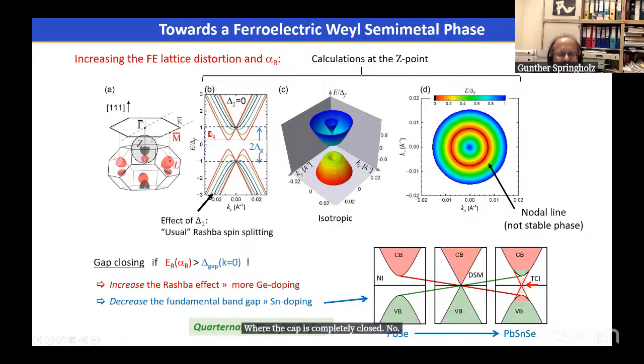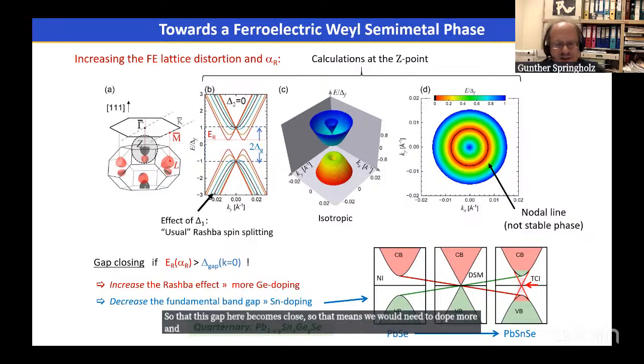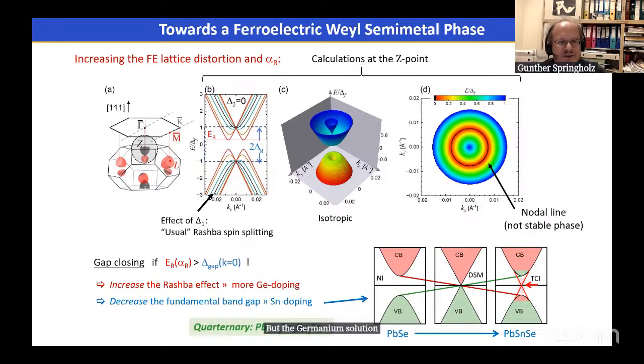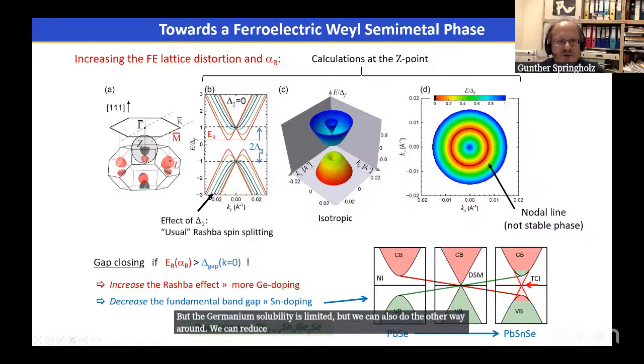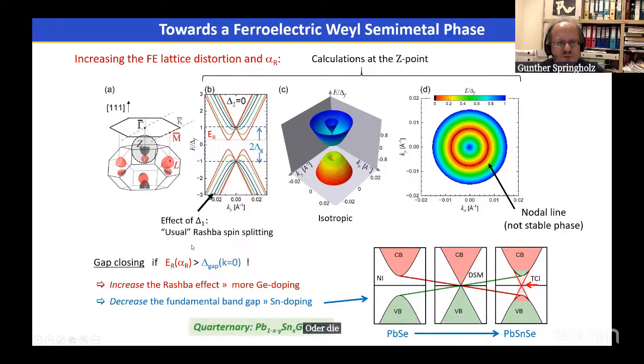Now, how can we achieve such a state? We can either increase the Rashba constant so that this gap becomes closed. That means we would need to dope more and more germanium, but the germanium solubility is limited. But we can also do the other way around. We can reduce the band gap of the system so that it is easier to achieve this condition that the Rashba energy gets larger than the band gap of the system.